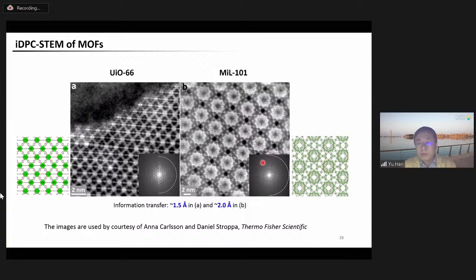As mentioned before, the advantage of iDPC-STEM is that the images are directly interpretable without the need of image processing. The directly collected image looks like this, and we don't need complicated image processing. We can get an interpretable image with iDPC-STEM. And the image contrast is also very good. So personally, I believe iDPC-STEM has great potential for imaging beam sensitive materials, and this great potential should be further explored.